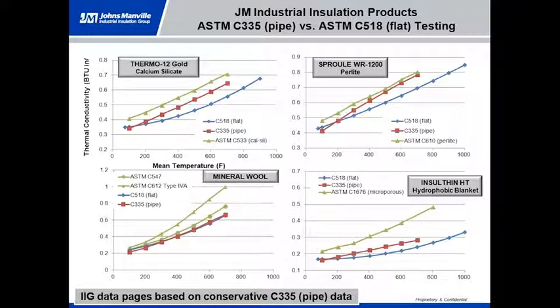If you go down to the lower left-hand corner, there's kind of an exception here. We talk about mineral wool. ASTM C547 is for the pipe configuration, and that has thermal values that are in the standard. And then there's also ASTM C612, which is a board standard specification, and that has different requirements, which you can see is the higher line of those two greens. But still, the product is well below those lines. And then, of course, we have microporous in the lower right-hand corner.